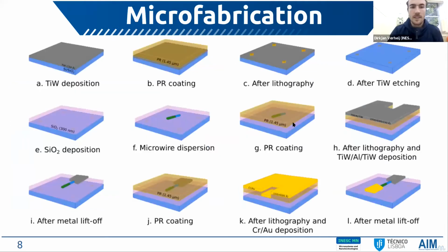So then with these wires, we create our radiation sensors. And in this slide, I show the several fabrication steps we follow at INESC MN. So we start with a titanium tungsten deposition, which after a lithography step and an etching step creates these small crosses on the substrate, which are alignment markers. And I will later on explain better why we need these alignment markers.